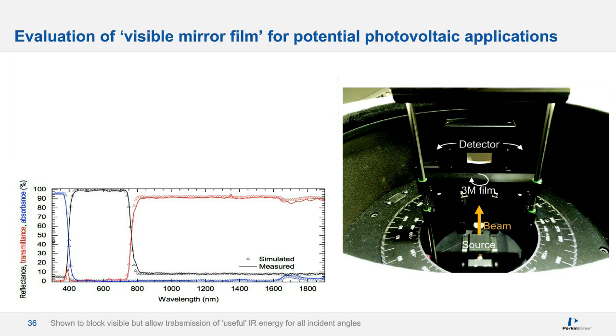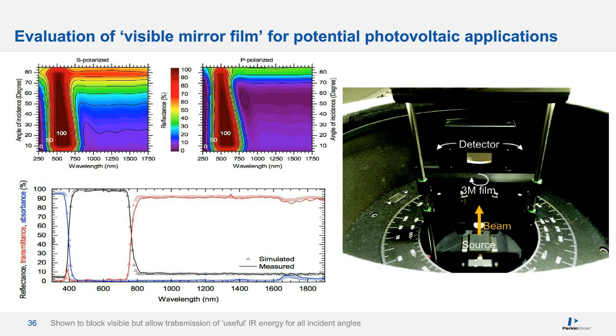It was anticipated that this type of film could be incorporated into a tandem photovoltaic, such that useful wavelengths of sunlight are collected, and the less useful wavelengths within the visible region could then be redirected to a second photovoltaic device with a more appropriate collection efficiency. As you can see from the reflectance and transmittance data collected at near normal incidence, the mirror film used here reflects visible light but transmits the vast majority of near-infrared radiation. A more exhaustive multi-angle measurement was then performed to see how these films would perform at any angle. The S and P polarized specular reflectance data show that the mirror retains its efficacy to block and transmit light effectively for all appropriate wavelengths of light for all angles.